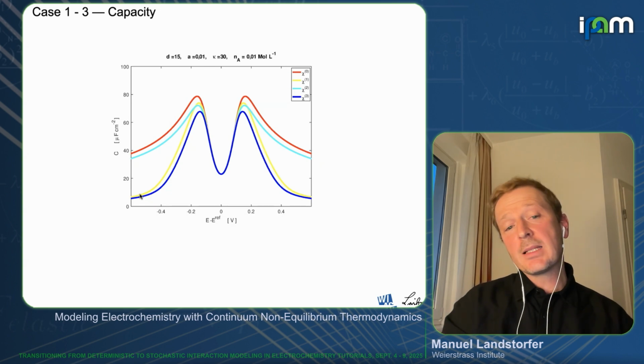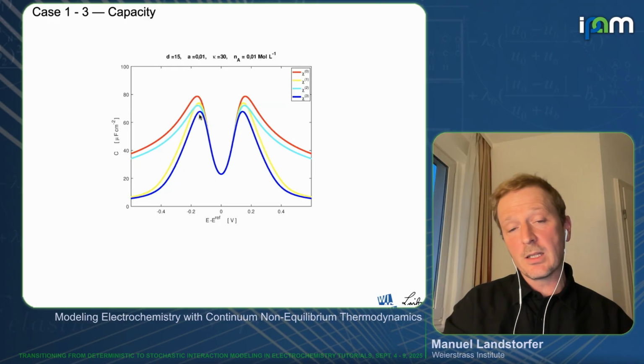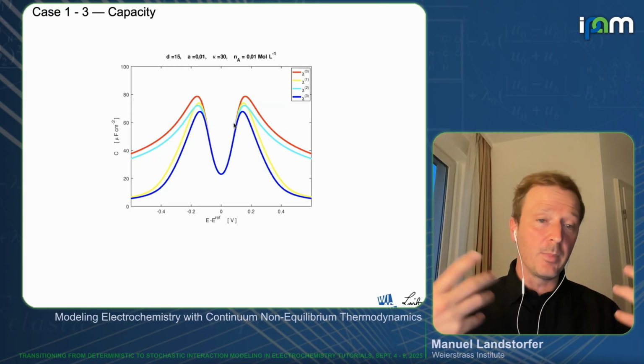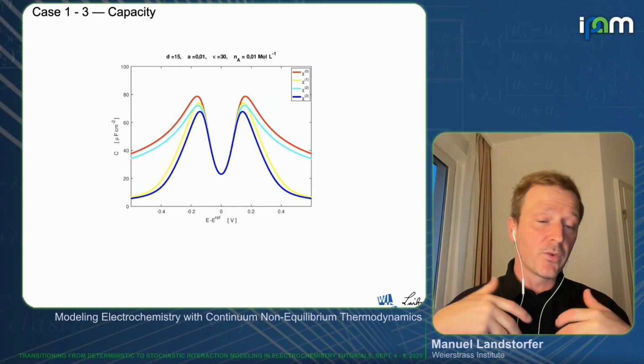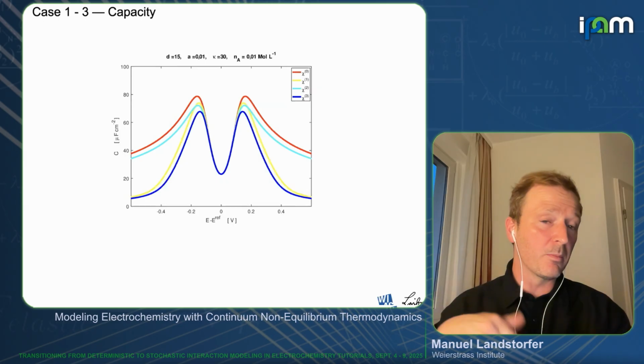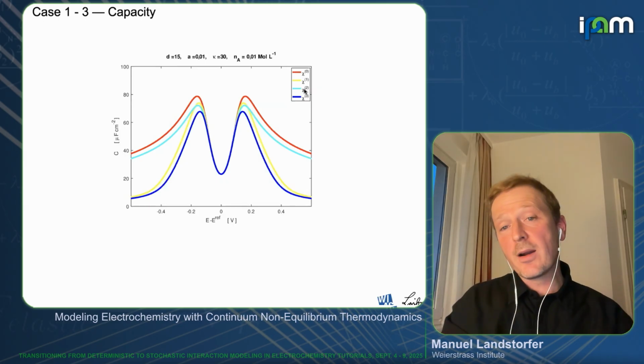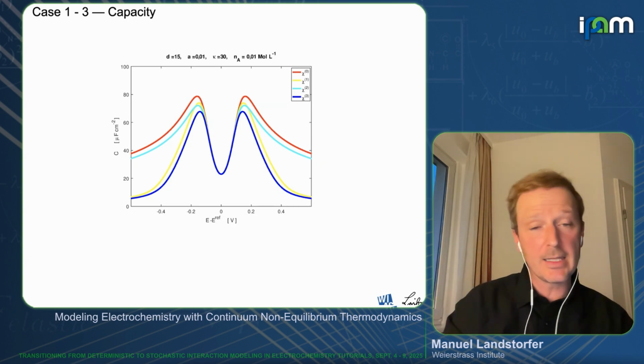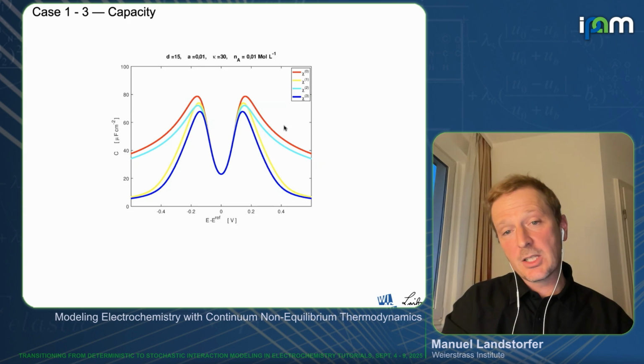And as you would expect, the field dependency really dramatically kicks in, in the sense that it's decreasing capacity values beyond minus and plus voltage values beyond the maxima. So in that sense, I believe that from, let's say, a broad data set of capacity measurements, you can basically reconstruct whether the electric field dependency of chi is as strong as Graham suggested or not.